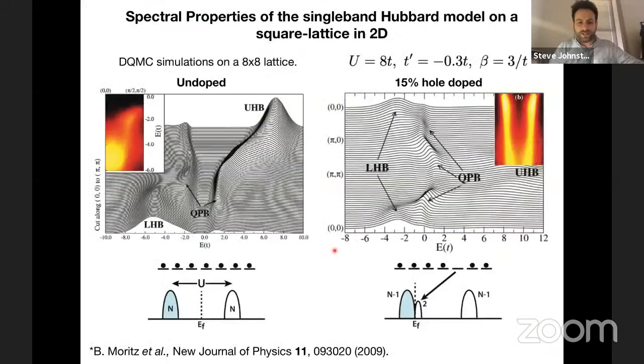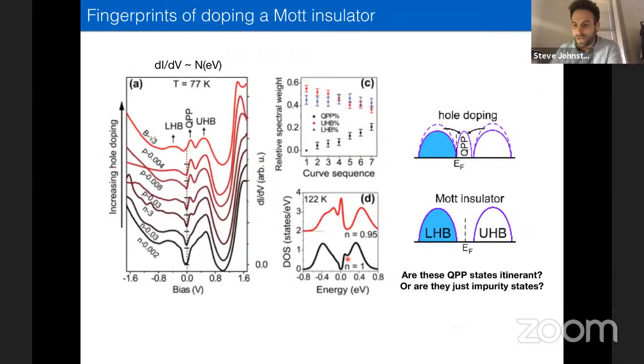Yeah, so we see it actually here as well. And when we do the square lattice calculations, it looks like these lower Hubbard bands sometimes have these sort of precursor quasiparticle-like states here. I don't really have a good explanation for them, but we see them pretty universally when we do numerical calculations of the Hubbard model. So I think what you're seeing here is sort of the equivalent of that on the triangular lattice. I think the single-site DMFT would not give you this, but some cluster theories, like dimer theories, have some sort of a magnetic exciton peak or something like that, even in the insulating state. Yeah, that may be the case. I mean, this is a cluster theory, so this is a 3x3 DCA cluster in a mean field. But yeah, we see it whenever we do these extended cluster calculations.